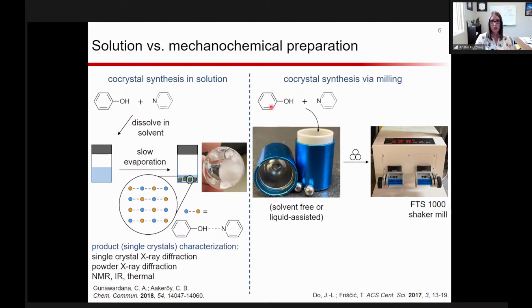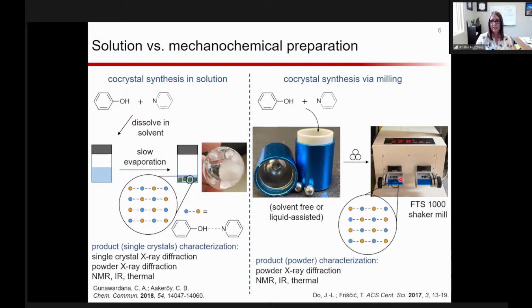In this case, you would take the 2 components and combine them into your milling jar, and we're using stainless steel milling jars as well as stainless steel milling balls. There's some flexibility in those materials as well, but that's what we're going to use for the whole talk today. And then you can either do this milling solvent free, where you add no additional solvent, or you might add a few drops of some organic solvent to assist in that milling process. Then you're going to mill at a certain speed for a certain amount of time. And in the same way, ideally at the end of this, you have a co-crystalline solid as your product. So you can characterize this. A lot of the times this is going to be a powdered material, so you can pull that out and characterize it by powder X-ray diffraction. And if you happen to have the single crystal structure, you could confirm that what you're getting by milling is either the same as what you get in solution, or maybe it's actually different.